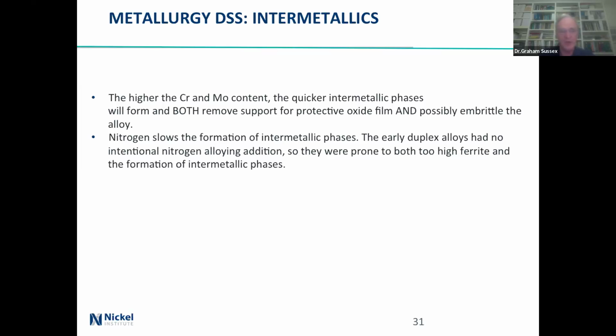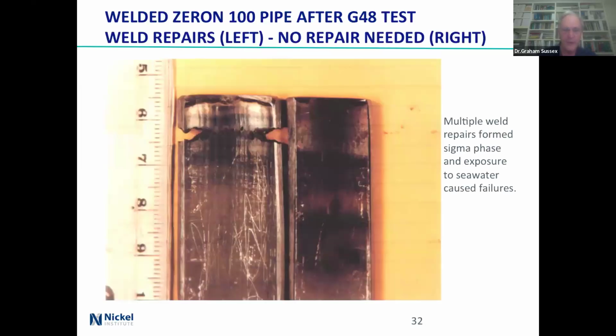If you're putting nitrogen in, as happens with the low alloys, then it slows down the formation of the intermetallic phases. But the early duplex alloys had no nitrogen control, and so they really didn't know where they were. And so they were very prone to both high ferrite and the formation of the intermetallic phases that you really don't want.